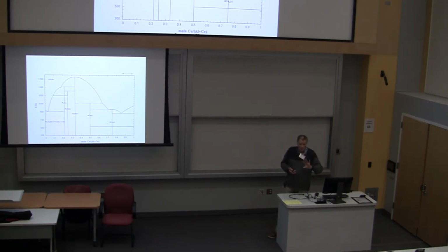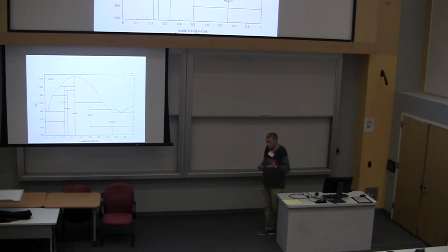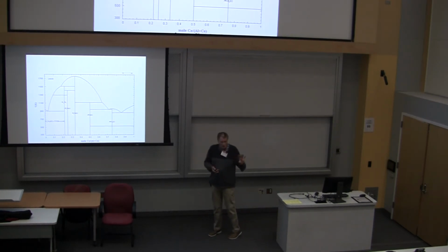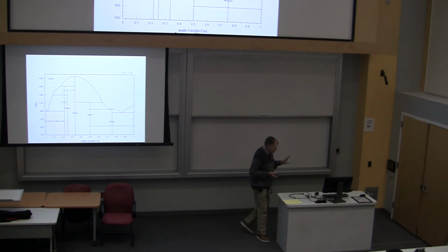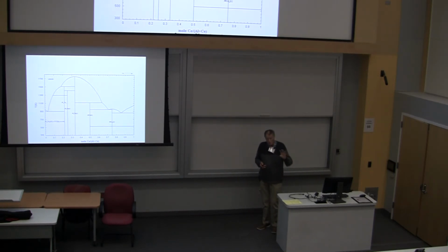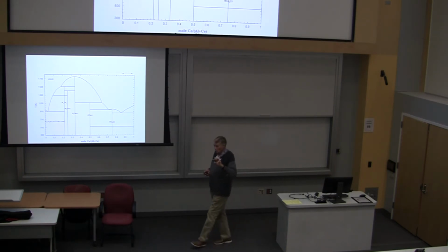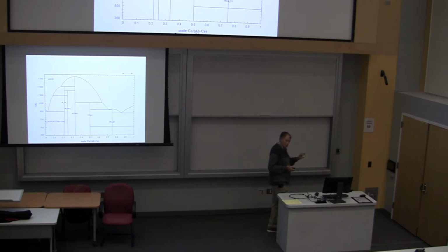So I was interested in resistance measurements once on rare earths. So I took some 3/9 lanthanum and annealed it, just from arc melting it. Arc melted a big pill, annealed it, took it out, and you could look at it and see it was 3 crystals. There were 3 domains in there. And so I got 4/9 lanthanum, I can't remember who I got that from, and did it, annealed it the same way, and got 1 single crystal.